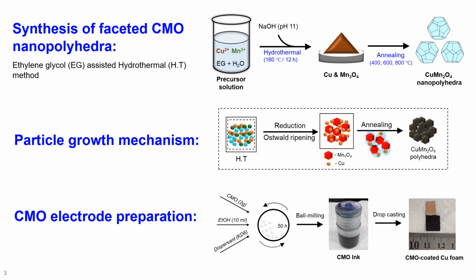And then the CMO electrode preparation. Here we have adopted the planetary ball milling method to produce high quality ink. In this process, 3 gram of our CMO, 10 ml of ethyl alcohol and 2% of KD6 dispersant are mixed together, and then subjected to the planetary ball milling process for 50 hours to produce the high quality CMO ink. And then this ink was drop casted on the cleaned copper foam to produce the CMO electrode coated on the copper foam, shown like this.